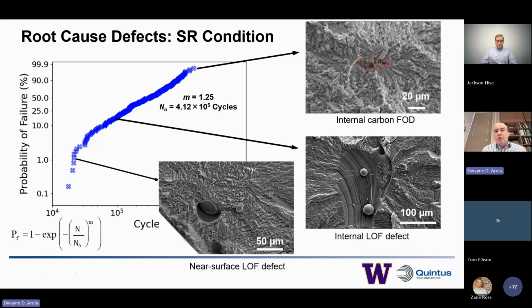These are representative, of course, of low, medium, and high life responses. So you're seeing at the low and medium life range two examples of void type defects which contributed to failure. And then on the highest end of the fatigue life response, an internal carbon FOD that's actually contributed to failure. These might not be unique from things that you see yourself, but the interesting thing for us,